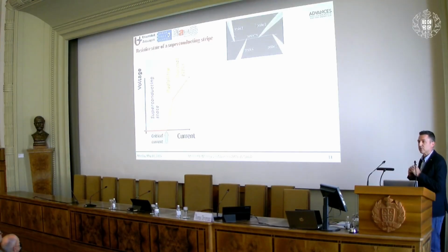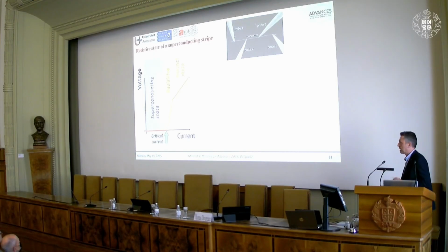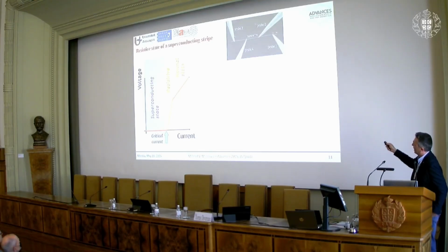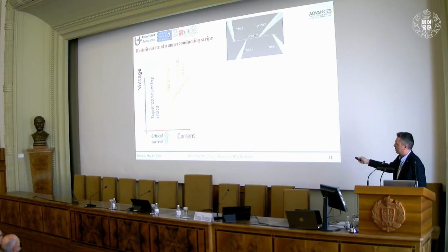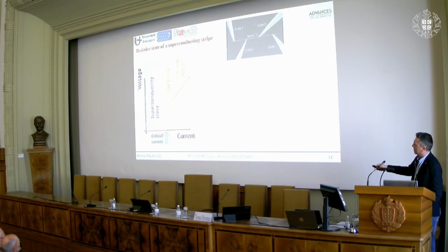So now I'm coming to the base of all the technology that I'm going to talk about. It's a plain superconducting stripe. It's as simple as it can be. So we have a superconducting nanowire. This is a typical 4-probe measurement. Here the current is applied, and here the voltage is measured. What do you get then? You get exactly a type of current-voltage characteristic like here: superconducting state up to some critical current, resistive state, and then normal state. This is ohmic resistance right here.